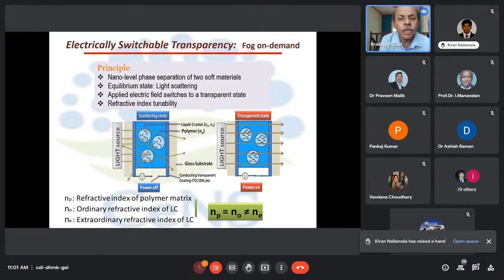The criterion to come up with such a display is that you have three refractive indices now. One coming from the polymer, referred to as N sub P, and two refractive indices coming from the liquid crystal, which we are already familiar with: the extraordinary refractive index N sub E, and the ordinary refractive index, N sub O. As we know for liquid crystals, I have already mentioned, Ne is not equal to N naught. That characterizes the liquid crystal. But by design, it is made such that the ordinary refractive index of the liquid crystal is made comparable to the polymer refractive index. And obviously now you might have already started guessing how the system functions.